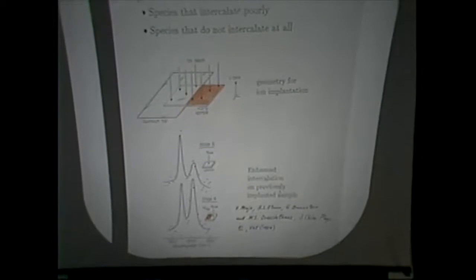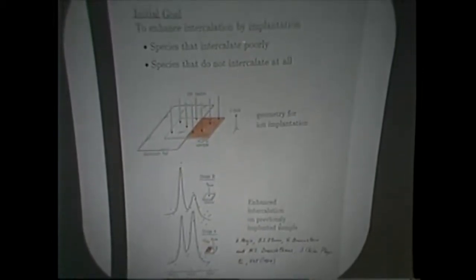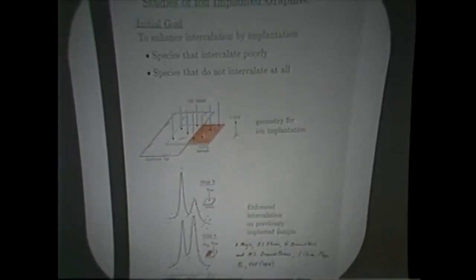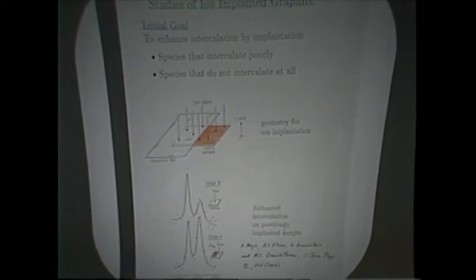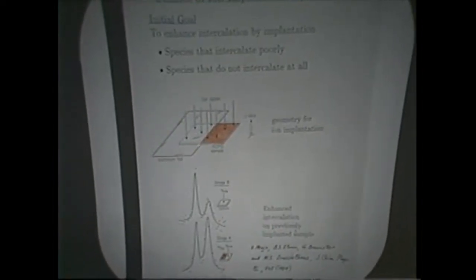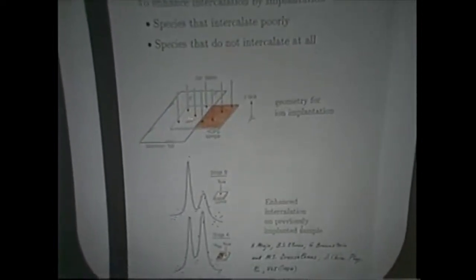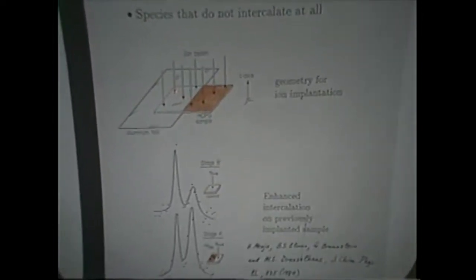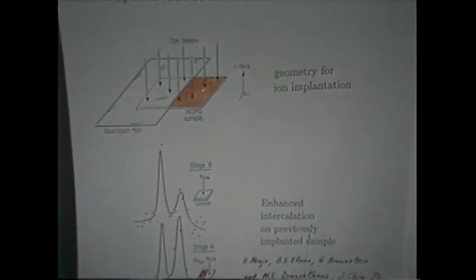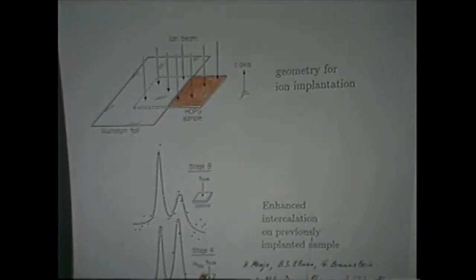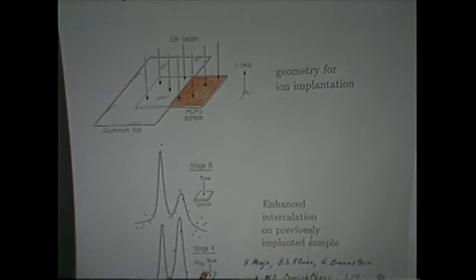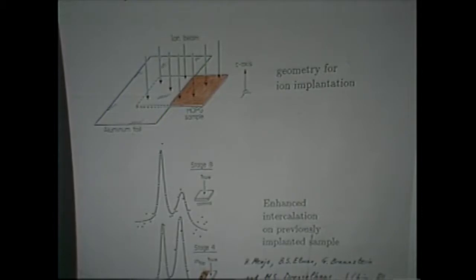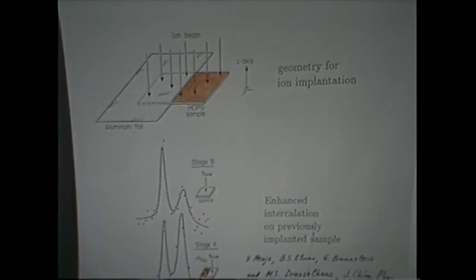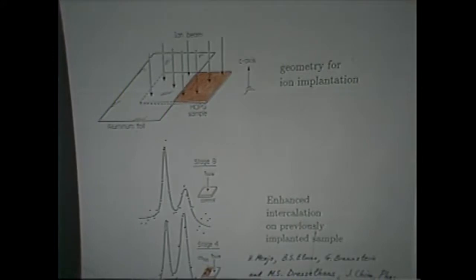Now, the idea is that we intercalate graphite with some species that either doesn't intercalate at all or intercalates poorly. So here's a test sample that we've implanted here, and this is a protection aluminum foil so that there's no ions going over here. And so we have the reference control specimen, and here's the implanted sample. And what we do then is we take the sample and put it into our ampule, and we start an intercalation, and we see if there is an enhanced intercalation in the region that's been implanted.